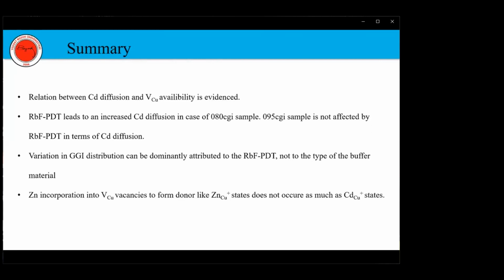We found that the variation in the gallium to indium plus gallium ratio distribution can be dominantly attributed to the rubidium fluoride post-deposition treatment, but not the type of the buffer layer material. Finally, we found that zinc incorporation into copper vacancies to form donor-like zinc copper plus states does not occur as much as cadmium copper plus states.